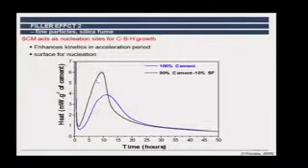And you see, it enhances the reaction of cement, but it also changes this slope here. This slope here is to do with the nucleation and growth of hydrates. And because we've got these very small silica fume particles, they give extra surface for nucleation, and they allow more hydrates to form. This is also why they produce materials which are higher strength, because there's a more even distribution of the hydrates throughout space.